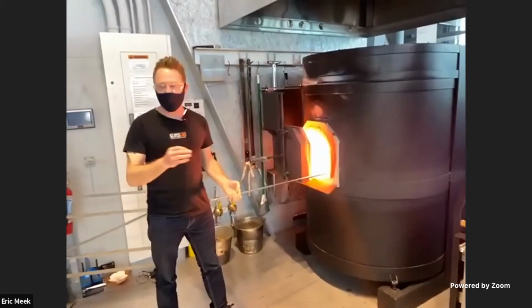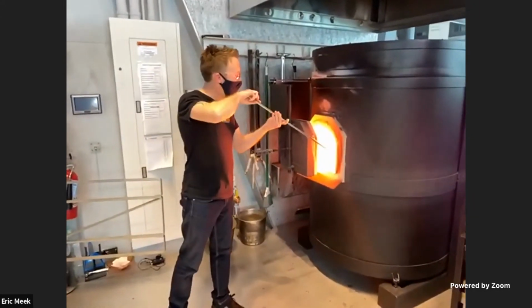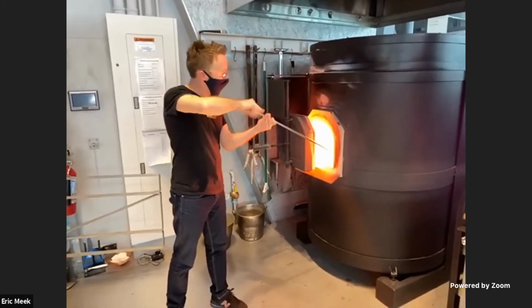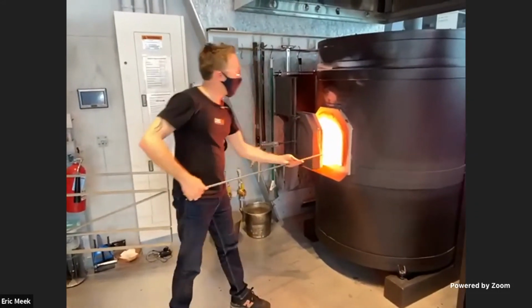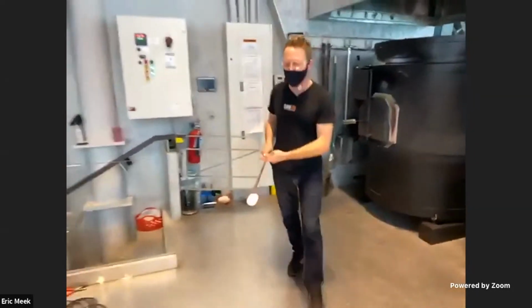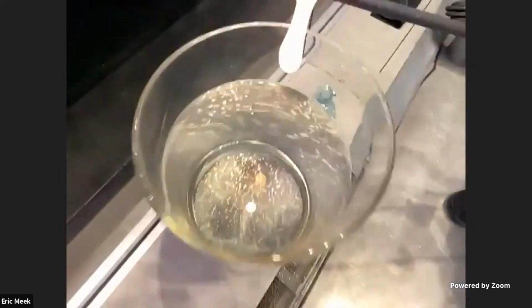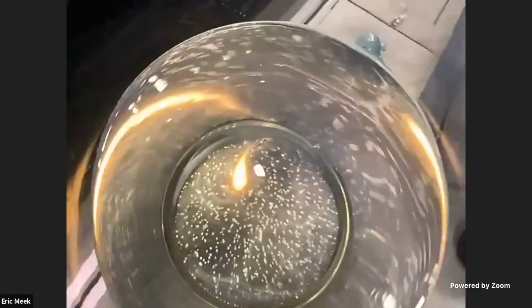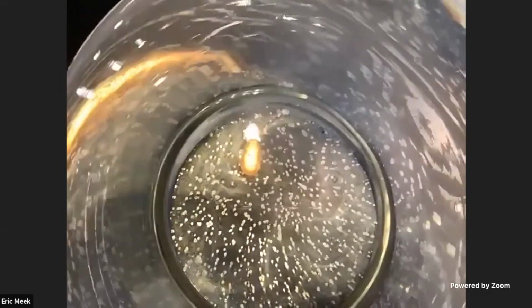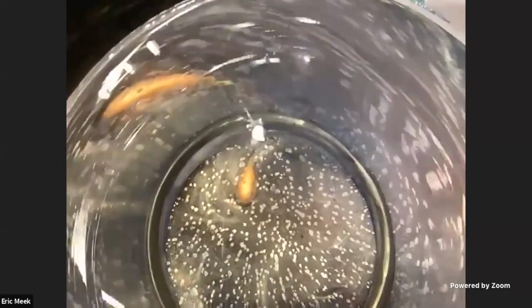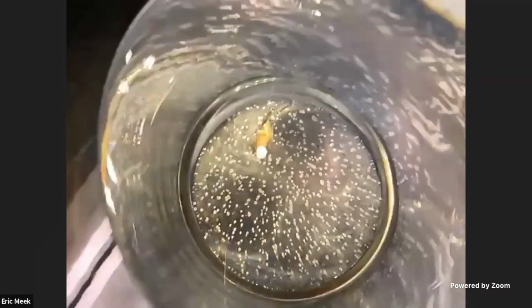What you're going to see is basically something that looks like a tadpole of molten glass. And watch very closely at that drop, the fattest part of it. That water is going to cool this drop from all sides simultaneously. And what that does is creates a lot of compression. So you can see how the outside of that drop goes clear very quickly because it's cooled so fast, but the inside stays hot longer, actually stays soft longer. As that inside is cooling, it's trying to pull in, it's trying to shrink from that movement that we talked about, but it can't actually move because the outside layer has turned rigid almost instantly.